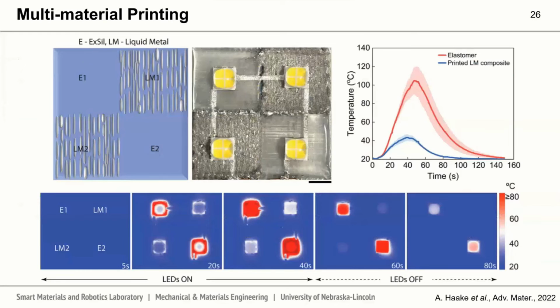We can add other print heads to our 3D printer, and now we can do multi-material printing, so we can embed highly thermally conductive heat sinks within traditional elastomeric materials. As expected, we see significant reduction in the heat around the light emitting diodes located in the bottom left and top right corner, where these heat spreaders are embedded within the material, and buildup of heat where the elastomer composite remains.